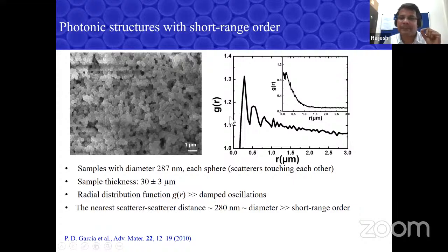What we calculate is a pair correlation function. Basically, I take a scatterer here and look at how many scatterers are nearby. If it is periodic, I get a huge oscillation because I can connect to the next sphere, and the next sphere like that. But if you look at the pair correlation function here, you see a bit of oscillation still at 1 micron. That means there is a short range periodicity preserved, probably over three lattice constants.